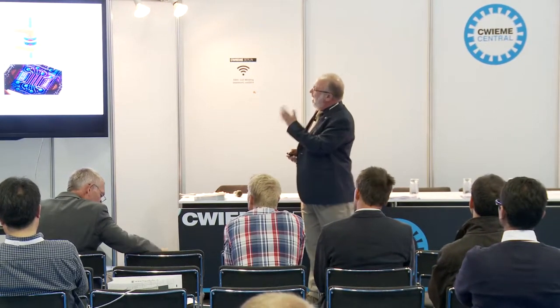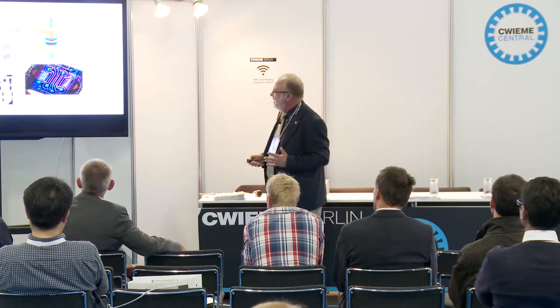There is also something called an exchange bias effect, where the hysteresis loop of a ferromagnet is not centered at zero field. It's displaced from zero field because this ferromagnet is in proximity or next to something that is not ferromagnetic, something that is called antiferromagnetic.